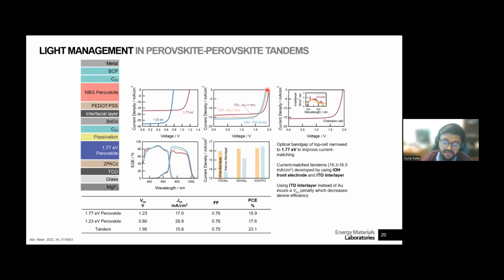But in this case, at least, the loss in the voltage is more than compensated by the gain in the current, right? So as a result, your overall device performance efficiency goes up. But the moment you change this gold layer for the ITO, and that's to go to the blue one, you improve the current for sure, but you now lose a bit more voltage, and that we think has to do with the conductivity of the ITO layer compared to the gold. And in this case, the current improvement does not really improve the overall performance of the cell. So optically, this would be most favorable, but if you take everything together, this one kind of works the best for us. So at the end, we can get a 23.1% tandem solar cell with it, and you can scale this up as well to a square centimeter.